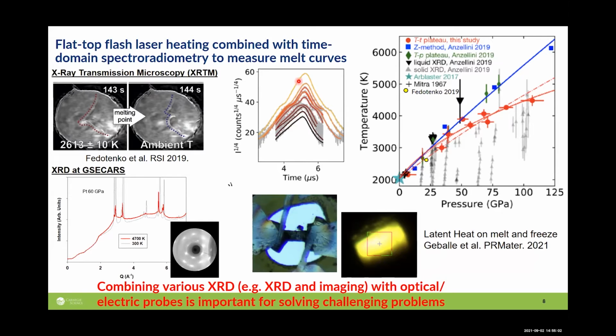And if you look at the temperature as a function of time on a microsecond time scale, using in this case a streak camera to determine temperature, and in this case it's just log counts, you can determine the melting curve just by observing a plateau as a function of time. And if you plot this kind of curve as a function of pressure, you see that it's really different compared to previous determinations. The reason is that different techniques may be looking at different stages of melting. So we need to combine many kinds of experiments to really establish where melting curves are.